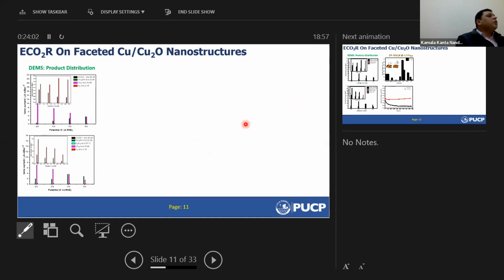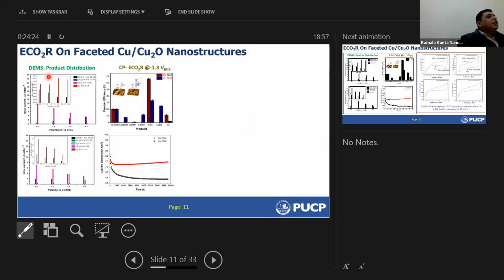For a quick identification of product distribution, we employed differential electrochemical mass spectroscopy. It is nothing but an electrochemical cell interfaced with a mass spectrometer and connected to a potentiostat or galvanostat to apply potential. We obtained methane on copper nanostructure A, with major 1-1-1 facets, and a mixture of C1, C2, and C3 products on copper nanostructure B, and the concentration of oxygenates was about 41%. We can see here also that copper nanostructure A only gave us C1 products, no C2 products were obtained, but here we obtained C1, C2, and C3 products.